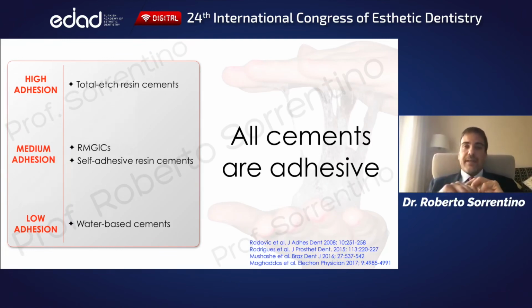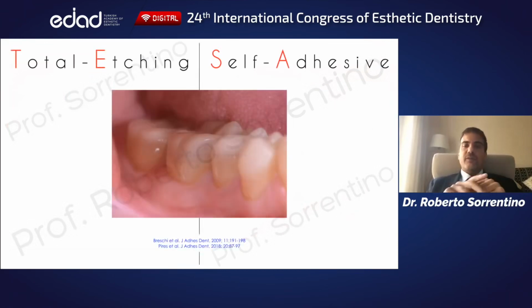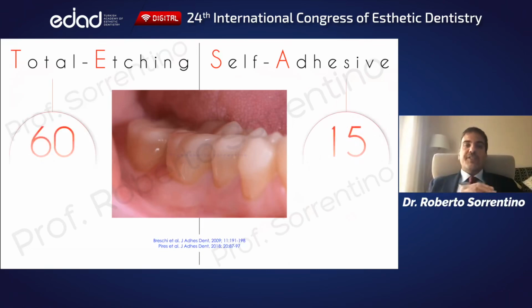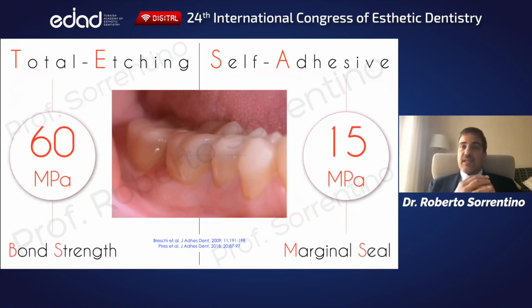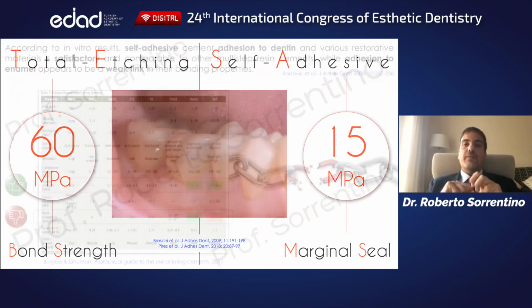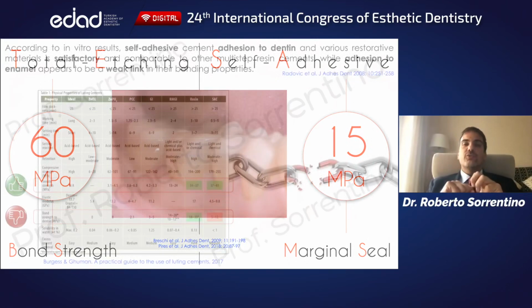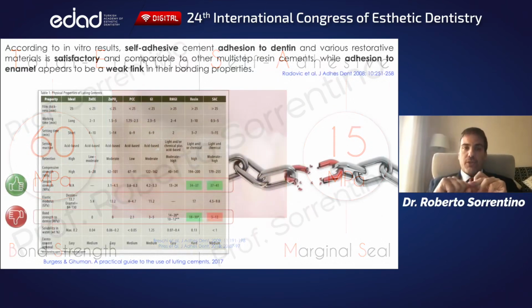As anticipated, the best bond strength values are offered by resin cements, but with great differences between the conventional three-step and the simplified self-adhesive cements. The former reach 60 megapascal, standing out for sheer bond strength, while the latter show 15 megapascal, mainly guaranteeing a good marginal seal. Self-adhesive cements are claimed as very easy handling materials due to their simplified adhesive approach.